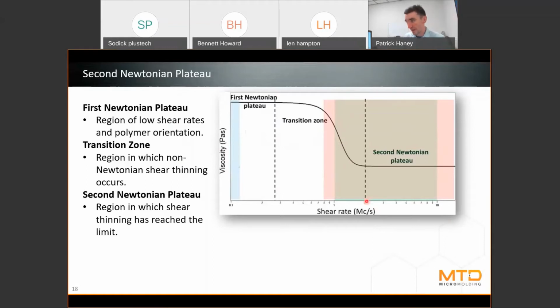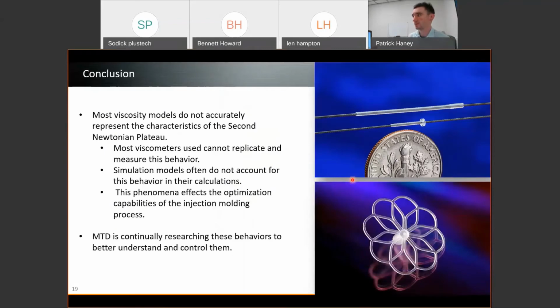So once we get into astronomical levels of shear rates that we might see in micromolding, we end up limiting out that shear thinning characteristic, and we once again plateau off to behave more like a Newtonian fluid would behave, where all of the laminar velocities are basically the same, and the benefits from shear rate are maxed out. Okay, so this region is a region that is greatly understudied, and it's understudied for a number of reasons, right?